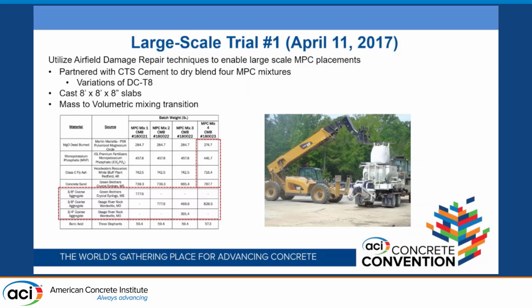So we used a local aggregate, the local to CTS aggregates, and then we used a 3/4 inch aggregate. And then MPC mix number 4, I altered the aggregate to binder ratio some. So I increased the aggregate to binder ratio. So those were the differences between the 4.